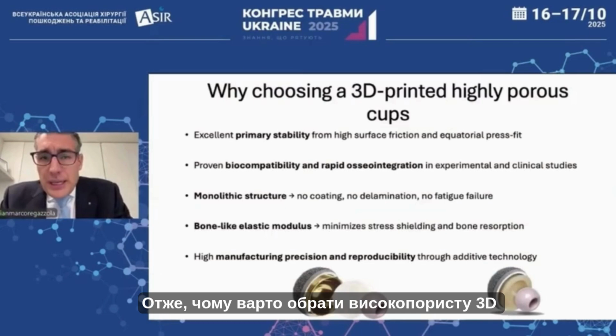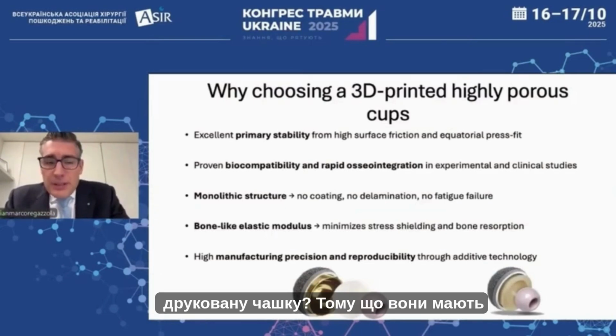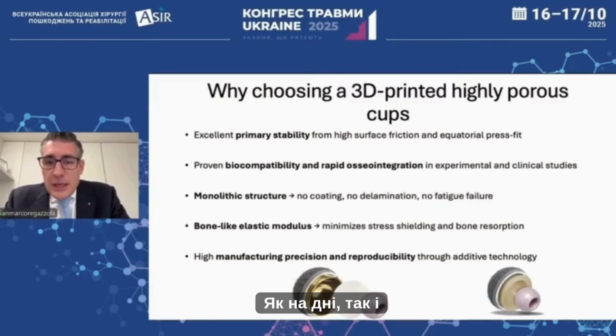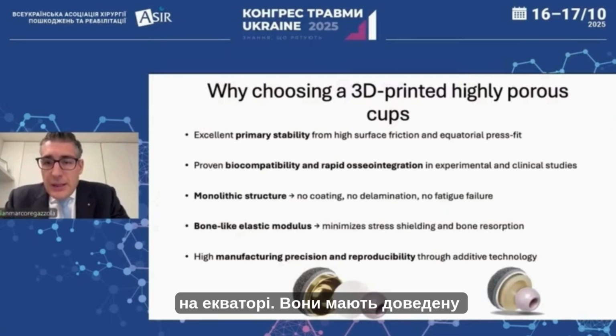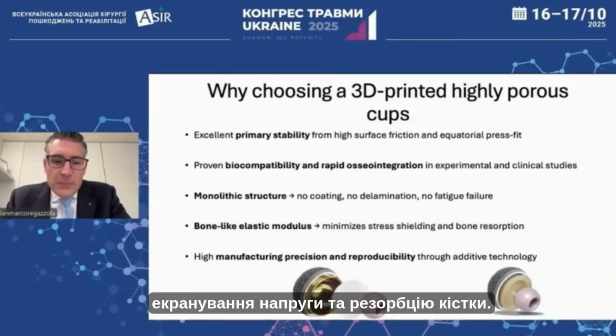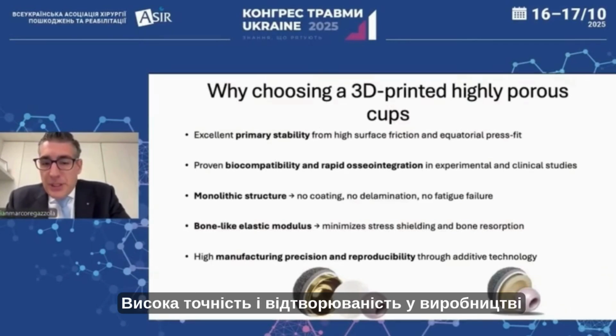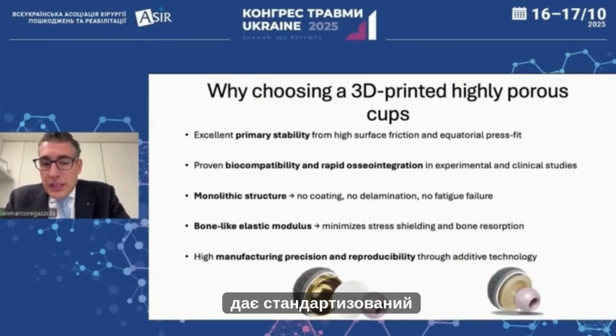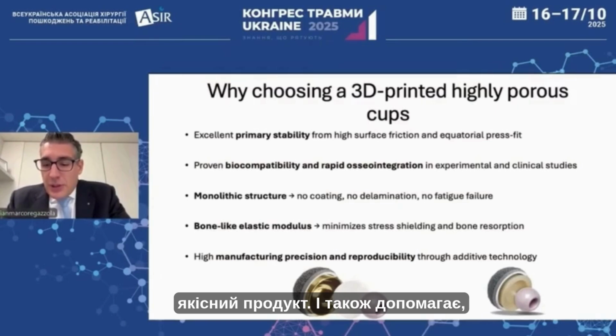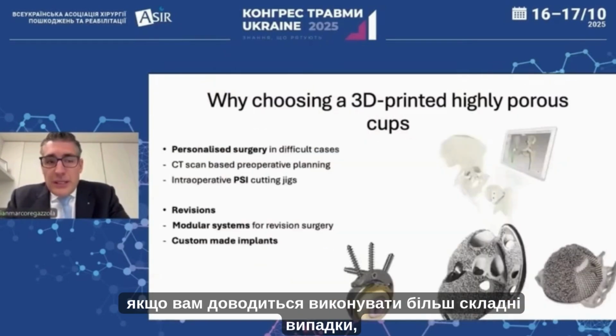So why choose a 3D printed highly porous cup? Because they have excellent primary stability, both at the bottom and at the equator. They have proven biocompatibility and rapid osseointegration. It's a monolithic structure, so there's no coating, no delamination, no fatigue failure. They have a very close modulus to host bone, which minimizes stress shielding and bone resorption. The high manufacturing precision and reproducibility gives you a standardized, qualitative product and helps you also if you have to do more difficult cases like personalized surgery.